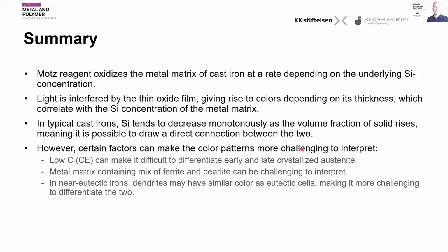So in summary, Motz reagent oxidizes the metal matrix of cast irons at a rate which depends on the underlying concentration. Light then interferes with this film, giving rise to colors depending on the thickness of the film, which reflects the underlying silicon concentration of the metal matrix. In typical cast irons, silicon tends to decrease monotonously as the volume fraction of solid grows, meaning it is possible to draw a direct connection between these two. However, certain factors can make the color patterns a bit more challenging to interpret.